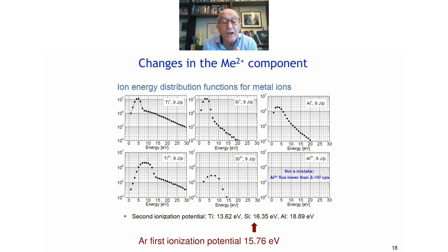Now, because we have argon to initiate the discharge, and argon is present even in the metal phase near the target, the argon first ionization potential is 15.76 eV. Titanium's second ionization potential is much lower. So having titanium produces both singly and doubly charged ions. For aluminum, the second ionization potential is almost 19 eV, so it is purely singly charged ions, while for silicon, it's on the borderline, mostly singly charged ions. Next slide.